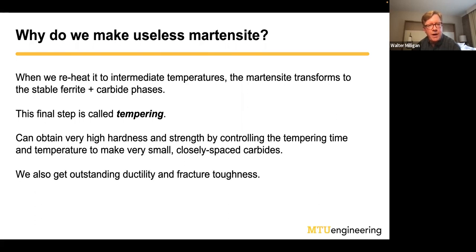And so when you see these products online or at the store and they say tempered, what they mean is that we had a 3-step process. We heated it up red hot to austenite, and then we quenched it, and we formed a really useless brittle phase. And then we reheated it a little bit and tempered it. And when we do that, we can have a very, very high hardness, and we can have very, very fine carbides, many of them that are very close together. And so we can get a very high hardness and a very high strength.